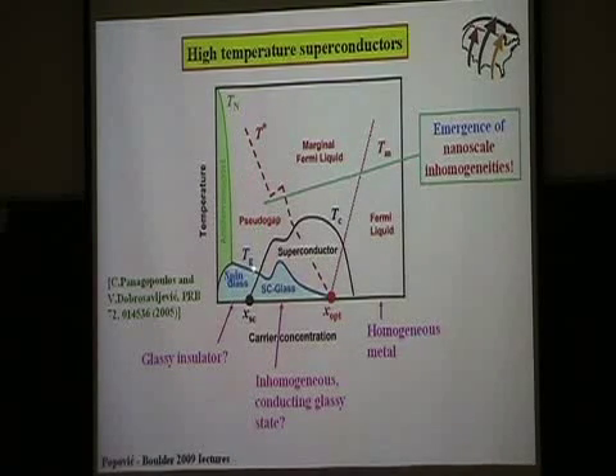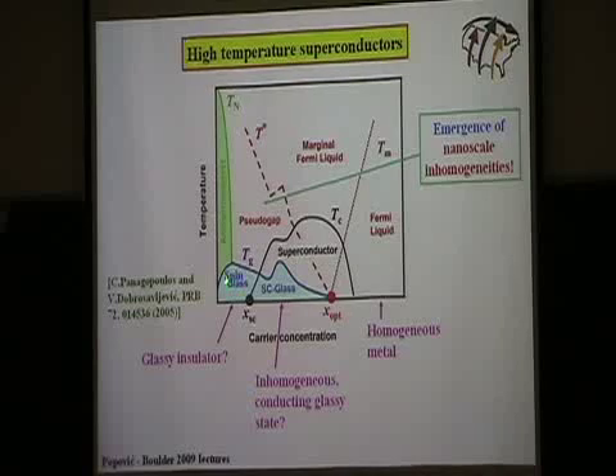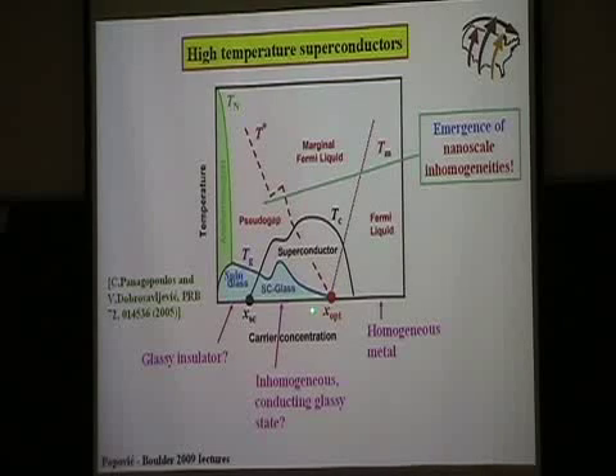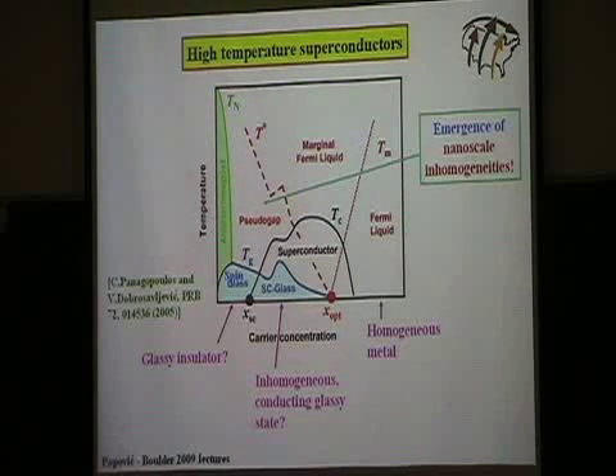So it has been established, for example, very well that at low temperatures the spins freeze. And you have the coexistence, and the spin glass phase extends all the way to this optimal doping. So here you have the coexistence of superconductivity and spin glass behavior. Now there are also some experiments that show the presence of some charge inhomogeneities. I showed some STM images before. These are local probes. There are also other probes, like nuclear quadrupole resonance, which is a local probe, and they also find evidence for charge inhomogeneities, but this is all done at very high temperatures.